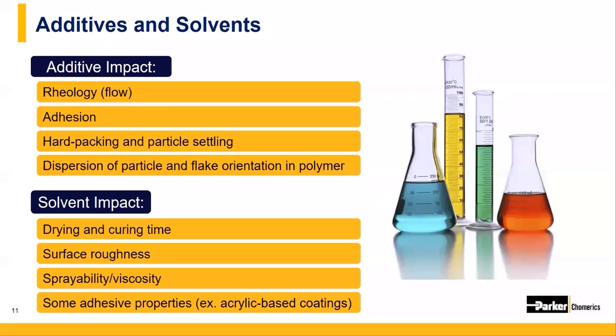Solvent blends of different evaporation speeds are used depending on the properties of the application and the specific design constraints to modify the drying time and curing time for each solution. For example, a self-leveling application would require slower evaporating solvents to allow the material to flow and settle properly. In the same vein, solvent evaporation rate can have an impact on final surface roughness as well as the viscosity of the paint during spraying. For example, overhead applications will require less dripping.